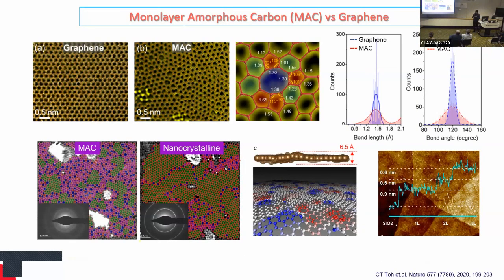Looking at the structure, what is the difference between graphene and monolayer amorphous carbon? You can see in the top corner: graphene has regular hexagonal carbon rings, but in MAC you have a very wide distribution of bond lengths and bond angles, and we mostly have 6, 7, even 8 member rings. So you can ultimately control how much disorder you want in the material.